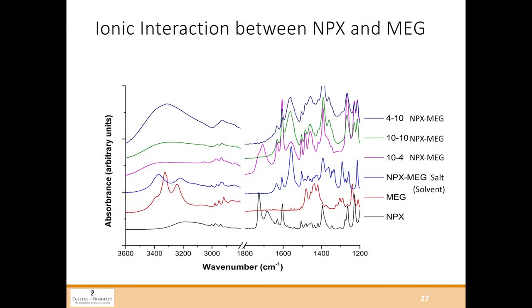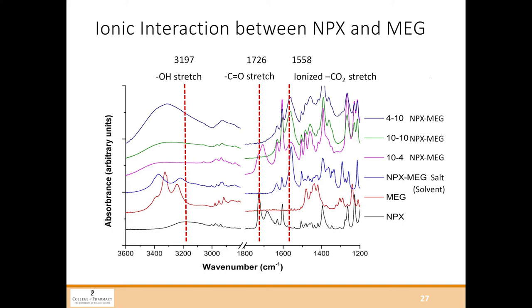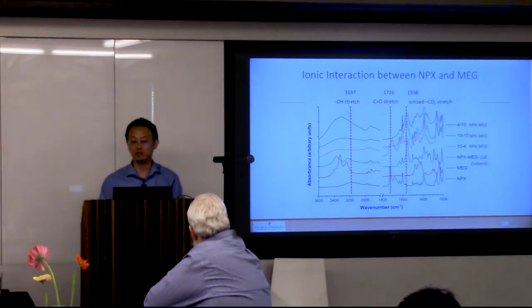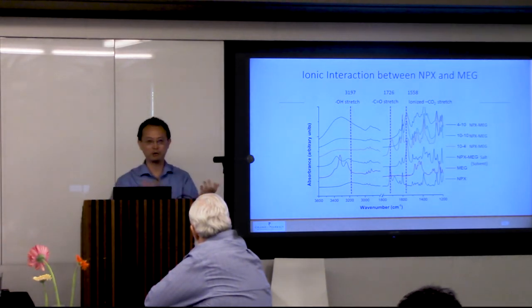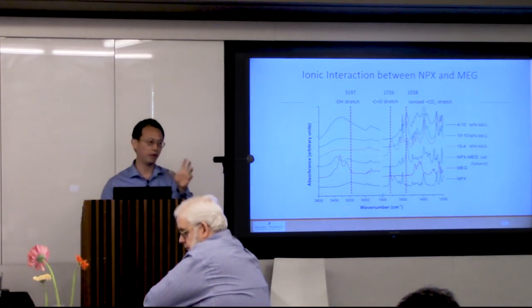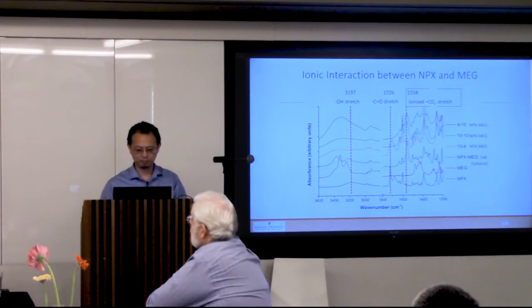When we look at FTIR analysis, if you look at naproxen itself, here's the carbonyl stretch, the unionized carboxylic acid from naproxen. Now, once we form a salt, if you look at this 1-to-1 ratio, in this green line here, the carbonyl stretch from naproxen actually moved over to the ionized. So from FTIR, we confirm it is in the ionized state, because there was always discussion about hydrogen bond versus ionization. I think based on the pKa, most likely they're ionized. It is ionized.